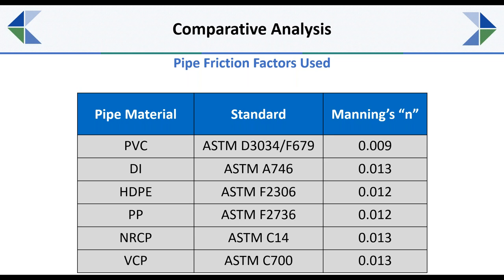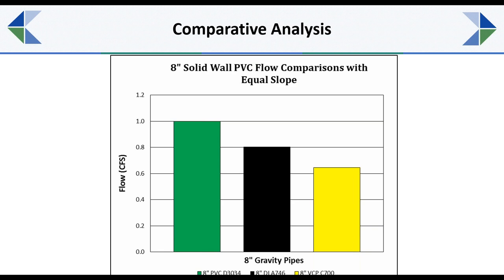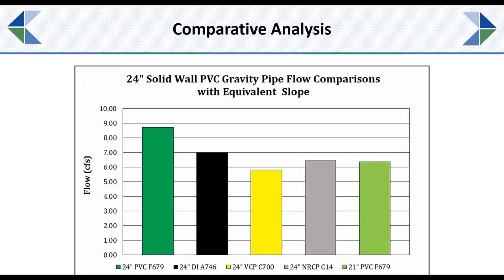PVC pipe is by far the most commonly utilized sanitary sewer material in the US and Canada. Approximately 90 to 95% of the pipe that's put in the ground today is PVC pipe, but we did look at those other piping materials. So these graphs here show if you took the 8-inch pipe, all the various pipe materials, and put them on the same slope, what would be the flow rate of the water going through those pipes? And so the higher the number, the better. And so in this case, PVC pipe does have the highest flow rate, which means it can handle the best amount of flow for the various products that we looked at.